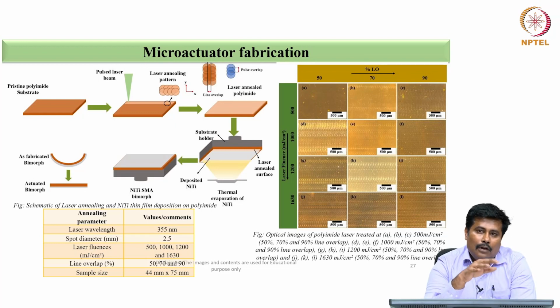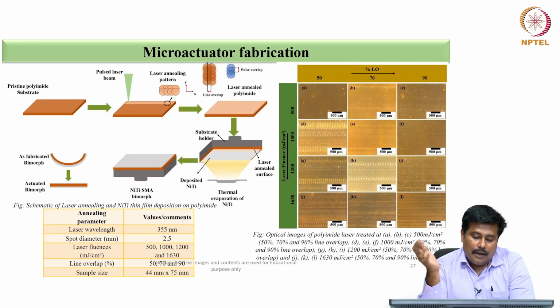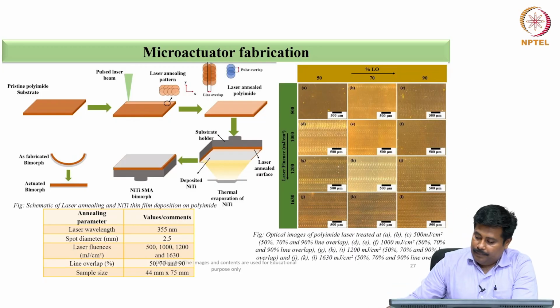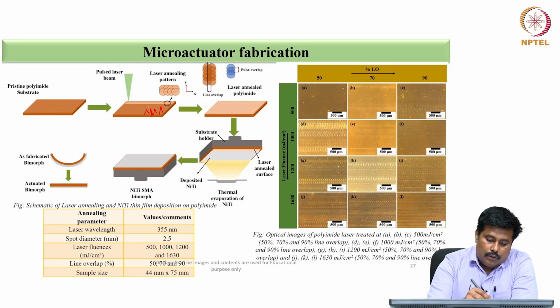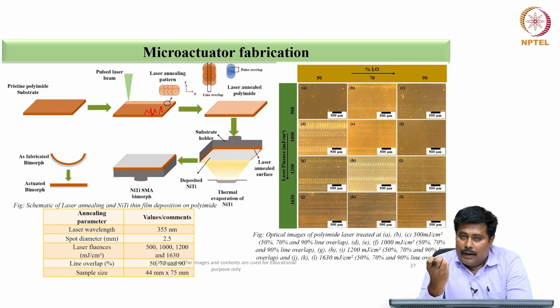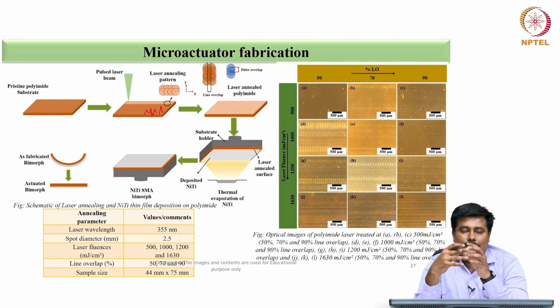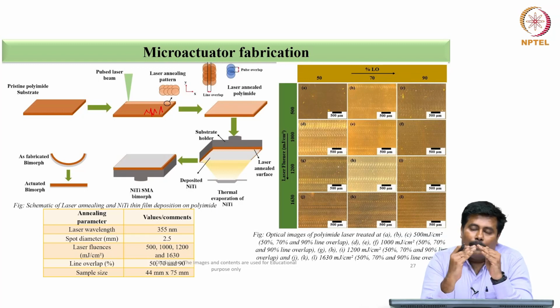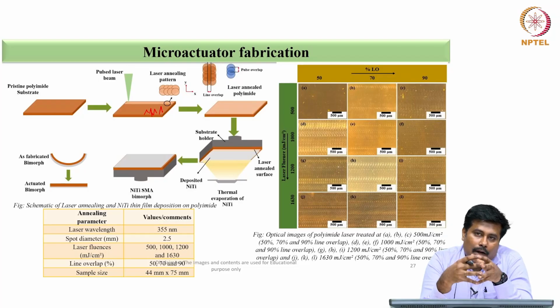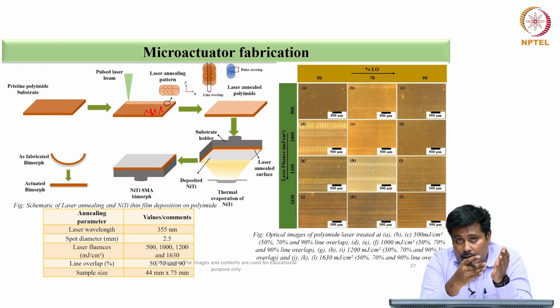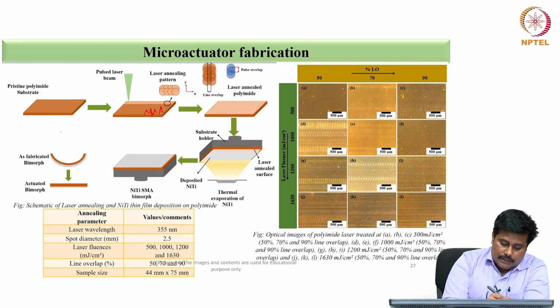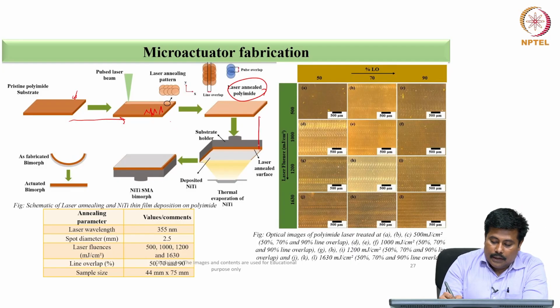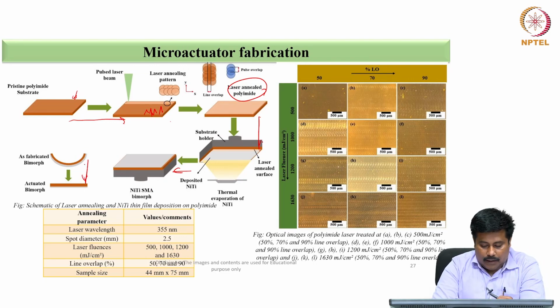Using pulsed laser crystallization, we can modify the surface based on the requirement, and then we go for a coating. Once we coat, these modified layers will act as an anchoring medium, and this anchoring medium will have more adhesion. That is, we are manipulating the surface to volume ratio so that you can have more adhesion, and with more adhesion you can have a larger life cycle, which is what we are looking for. So these are the overall steps followed. This is a pristine polyimide substrate which is integrated with laser annealing, and after the laser annealing the deposition is performed using thermal evaporation. With the thermal evaporation, the NiTi SMA bimorph, the as-fabricated bimorph and the actuated bimorph are integrated over here.